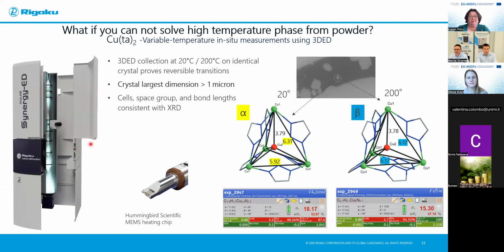So what happens if the phase transition is more complicated than we showed here? Sometimes the change is so drastic in your MOF that you are stuck and you cannot solve the crystal structure from powder. So you basically can prepare your powder, open the reactor, take the leftover powder and go to electron diffraction. We will talk, and I will introduce the instrument slightly later, but I just want to show you here that you have an option to use